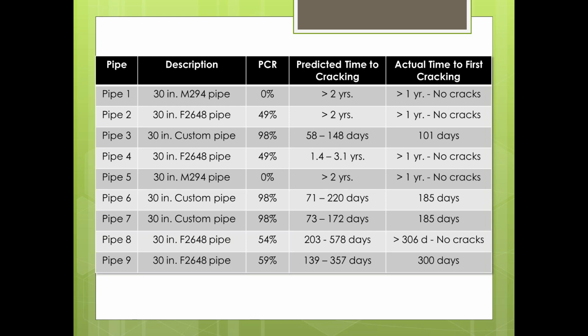So the news from the second part of the testing that was really exciting was that the predictive modeling from the UCLS test and the last NCHRP reports really provided a very conservatively accurate range for when the first time to cracking is really witnessed and observed in the pipe wall itself. So you can see in some of the pipes where the predicted time to cracking would be between, let's say, pipe 6, 71 to 220 days. The actual time to first cracking that was measured and recorded was right around 185 days. And that really held true for just about every single pipe that was tested.